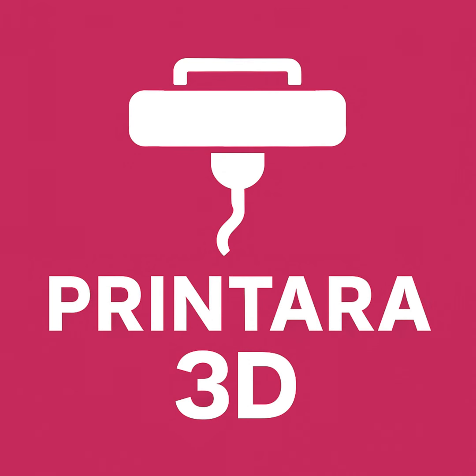Nothing else. You do not tweak the temperature. You do not mess with the cooling fan. You do not change the print speed. You only change the flow rate. You print the gear again under identical conditions. You examine the new top layer. Is the scarring completely gone? Is it slightly better but still visible? If it's better but not perfect, you reduce it by another 1%.